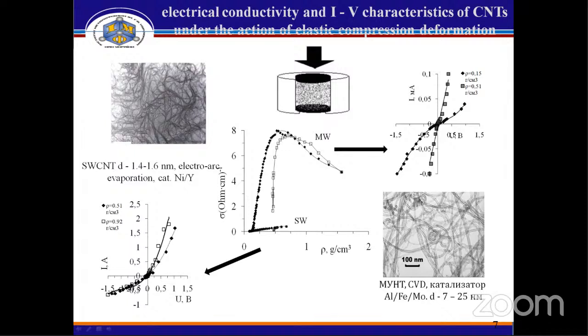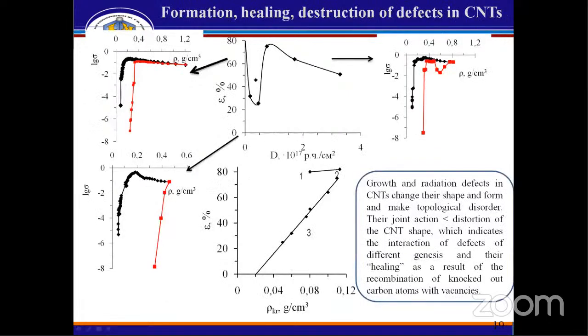In the situation with single-wall carbon nanotubes, electrical conductivity is 50 times lower than multi-wall ones. This difference is due to the different types of conductivity in CNTs. At low densities, the volt-ampere characteristic of the multi-wall carbon nanotubes has a non-linear symmetric form, which indicates van der Waals interaction and tunnel transitions. At high densities, it is a linear dependence, so metal conductivity, and the single-wall nanotubes have an asymmetric volt-ampere characteristic for all compression densities, which indicates the semiconductive nature of the conductivity. It's shown in these represented colors. Penetrating radiation causes not only radiation damage to materials, but also serves as an effective technological tool for improving the quality and obtaining materials with fundamentally new properties.